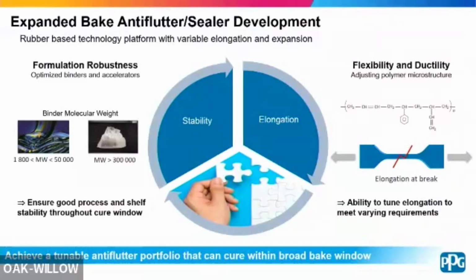On the elongation side, so thinking about flexibility and ductility, how do we adjust that depending on, again, the specific need, the location of where it's going to be applied on the vehicle, if we need more of a sealing functionality versus a high elongation functionality or a gap filling functionality. And really you can achieve that by adjusting the polymer microstructure. So just showing a very basic chemical structure here, but you get the idea, where we can adjust that microstructure to tune that elongation. And we're primarily measuring that using a standard tensile test with those dog bones, where you pull them apart until they break. And we've developed this tunable portfolio where you can tune that elongation to meet varying requirements.